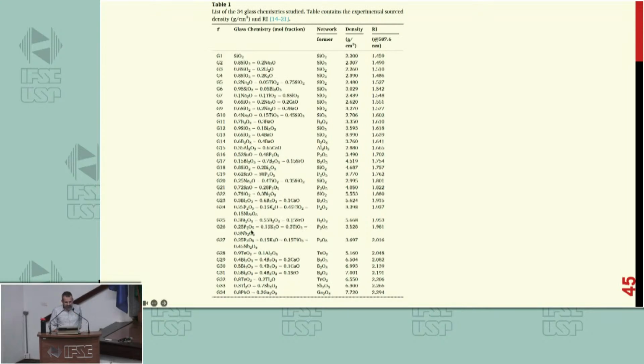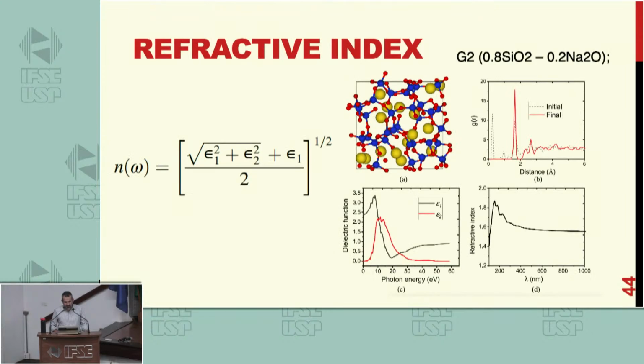And they made ab initio simulations for a lot of different stoichiometries of glasses. I cannot read. This is pure silicon oxide. This is 80% of silicon oxide and 20% of sodium oxide. A different stoichiometry, I cannot read here. Can you read? Sodium, titanium, and silicon. There are some that are more complex. Fluorine, potassium, titanium, and silicon. And niobium. So they ran a lot of ab initio calculations for a lot of glasses and calculated the refractive index for all of them. Here are just some examples.